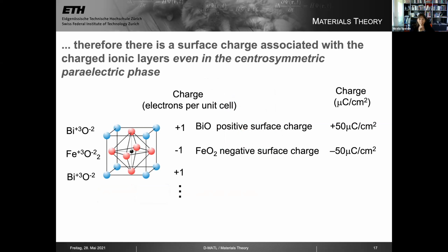As a result of this, because my bismuth ferrite in its centrosymmetric phase doesn't have zero as an allowed value of its polarization, there is a surface charge associated with the polarization even in the centrosymmetric paraelectric phase. And maybe it's even more conceptual to think of it in this cartoon way. This layer which contains bismuth and oxygen is a positively charged layer. So if I put a surface above that, I'm going to have a positive surface charge. This has nothing to do with any ferroelectric polarization. It's because of the internal layers of the material. Likewise, if I make the surface just above the FeO2 layer, I'm going to have a negative surface charge associated with putting the surface just there.